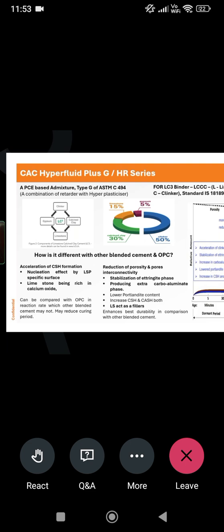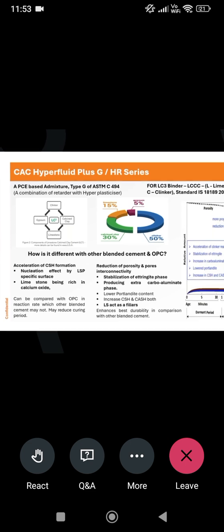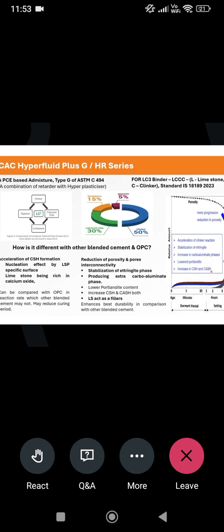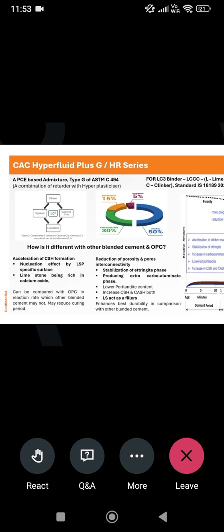And now this ettringite, after formation of ettringite, excess alumina comes from C3A and makes it monosulfate. Monosulfate's specific gravity is higher than ettringite, it is 2.2, 2.3. So what is happening when SG is higher? What does it mean? Volume is lower. So volume is lower, like this. Either further, this is the gap. These are the voids, from one ettringite to another ettringite. Now ettringite is converting to monosulfate, so the void is enlarging. So destabilization of ettringite creates more voids.